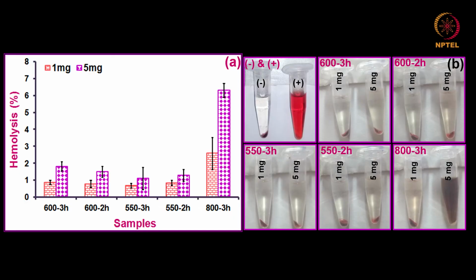Generally, as per ASTM standard, below 2% lysis is compatible. Between 2% and 5% is slightly hemolytic. Beyond 5% is highly hemolytic. So, a material should show compatibility below a 5% rate, then only it is acceptable for biomedical applications. With this study, I have analyzed the erythrocyte compatibility rate of bioactive glasses.